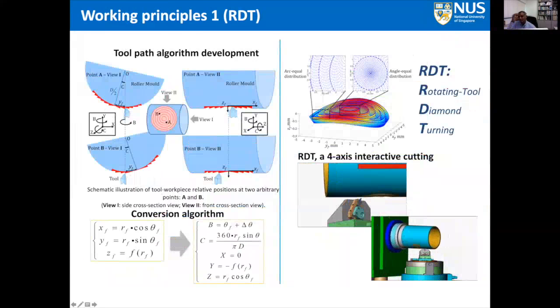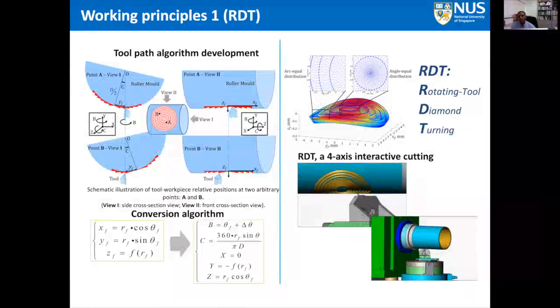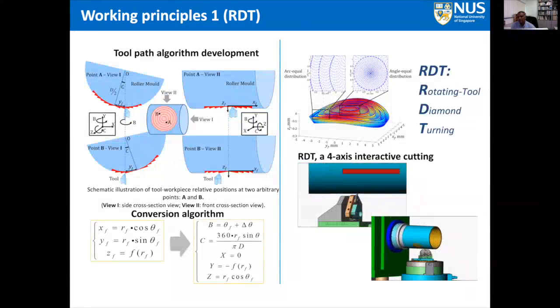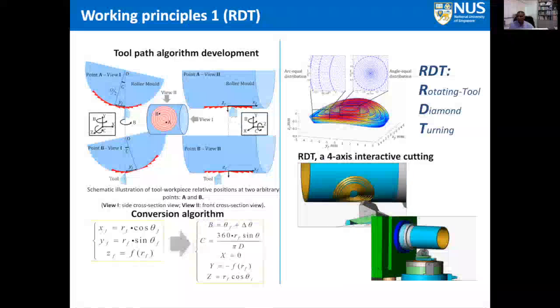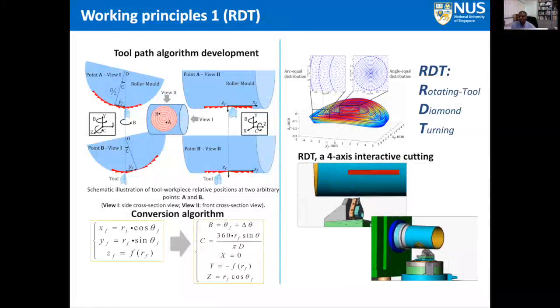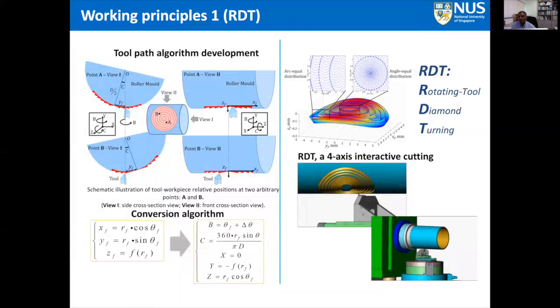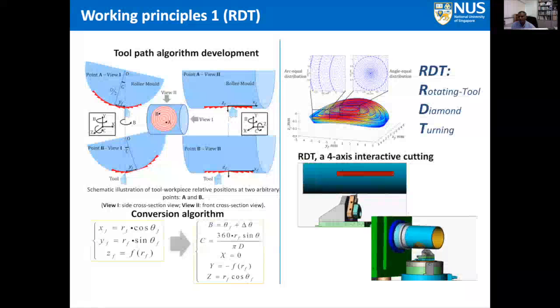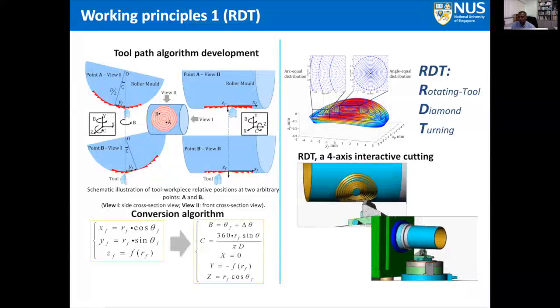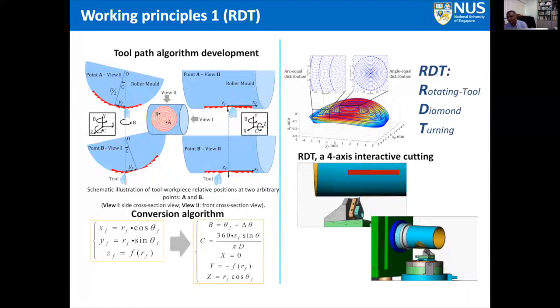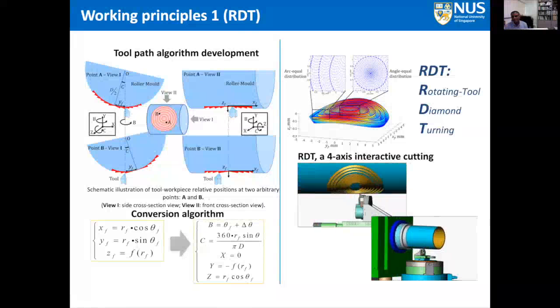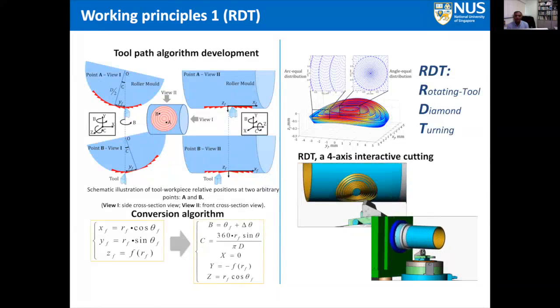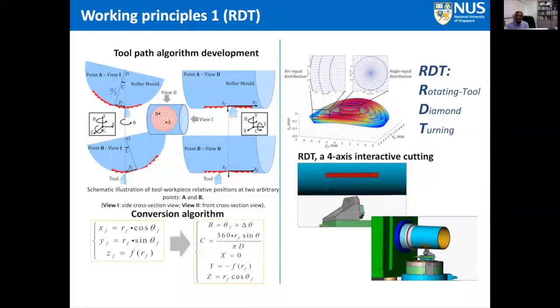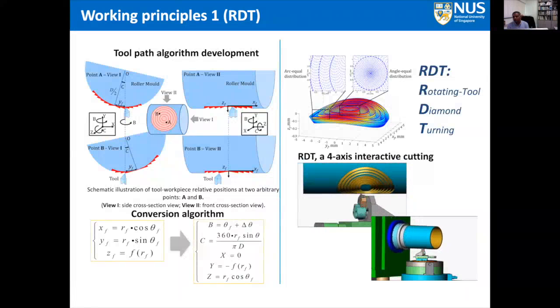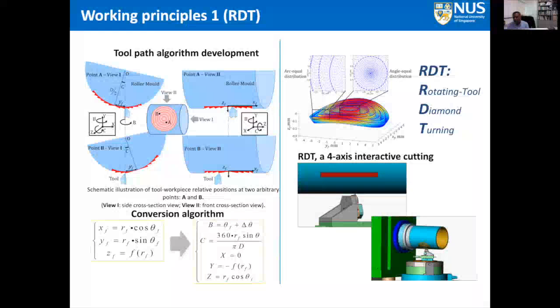So in this case, what happens is that we are trying to simulate or create a geometric relationship between the tool and the workpiece in relation to the arbitrary points by synchronizing the tool and the roller rotating process. So in the machining process, the C and Z axes are programmed to perform a kind of rotary motion between the roller surface and the tool tip, and achieve the turning process.